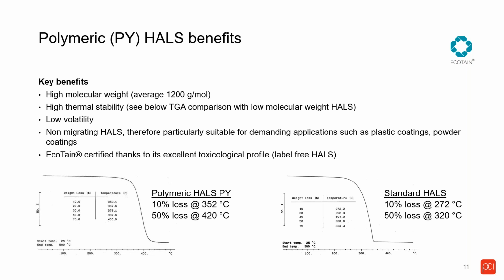And in this case, nothing better than a polymeric HALS, because when you have a polymeric HALS, you have this high molecular weight, and we know consequently that this will have an impact on the TGA. And that's what we see here.